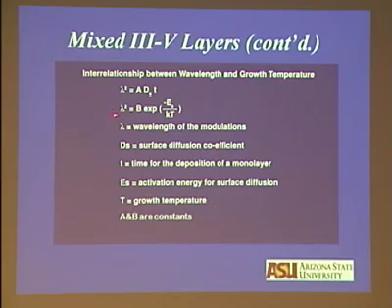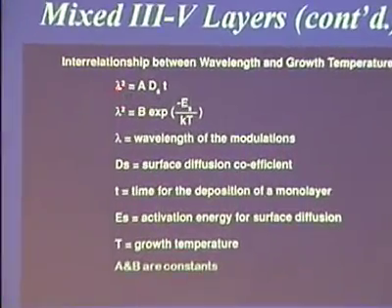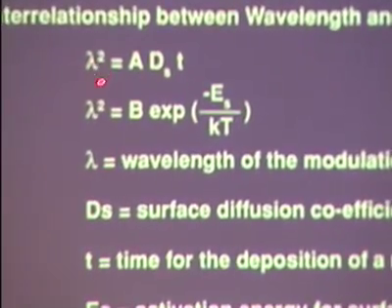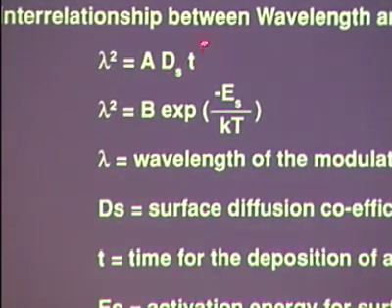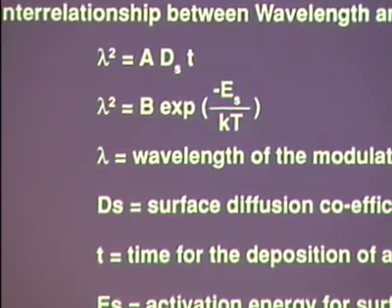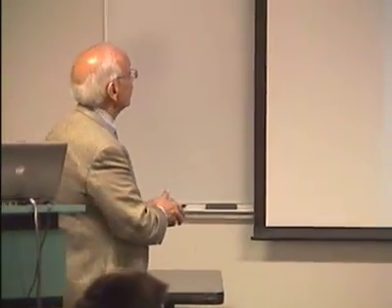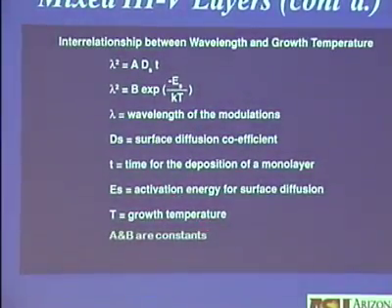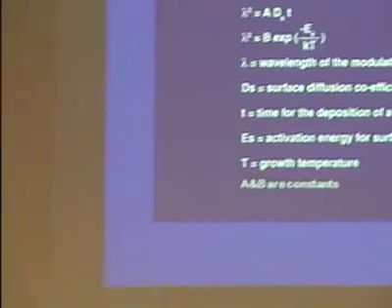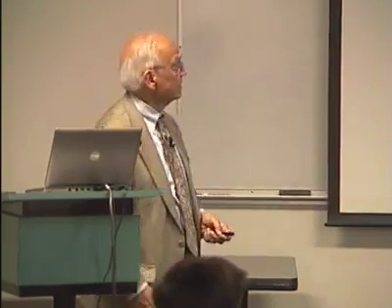You can write a simple expression. The modulation wavelength is related to some constants: A, the surface diffusion coefficient, and T, the time we take to deposit a bilayer. Once the bilayer is deposited, the diffusion of atoms cannot occur. This is the assumption we made. And you go for the activation energy for surface diffusion, the growth temperature; A and B are constants. So we measured the wavelengths of modulation from the diffraction patterns, then correlated them, and the fit is fair,